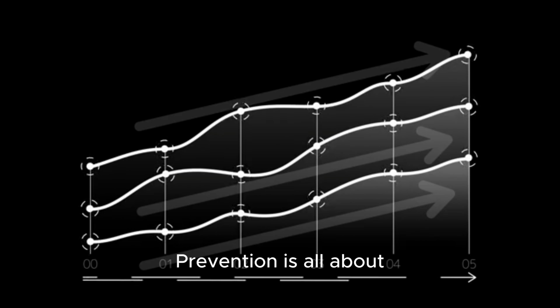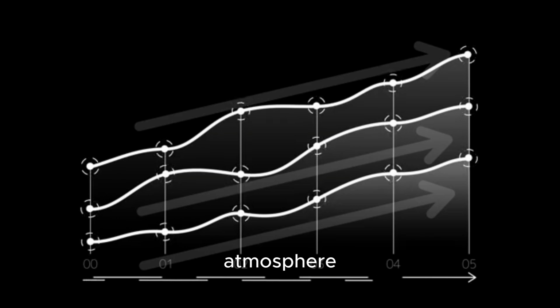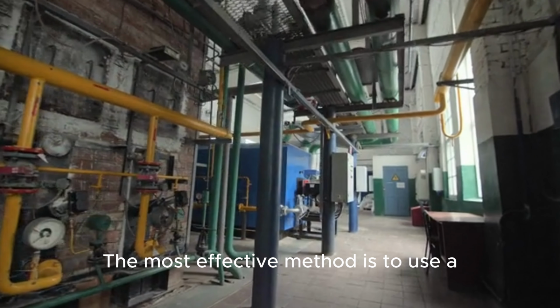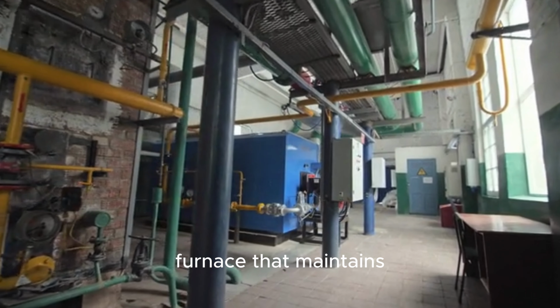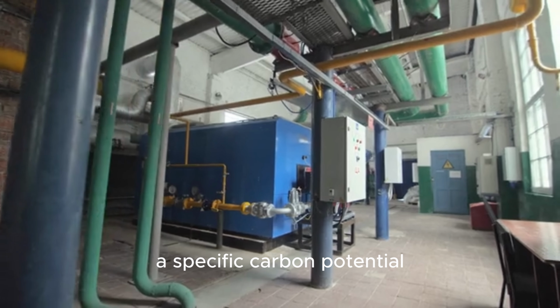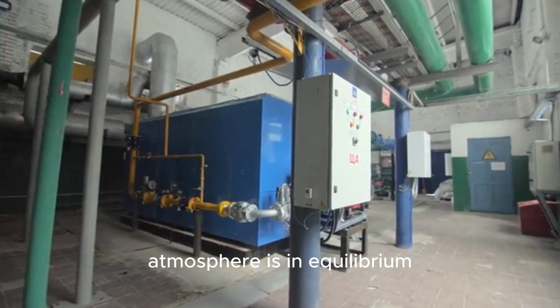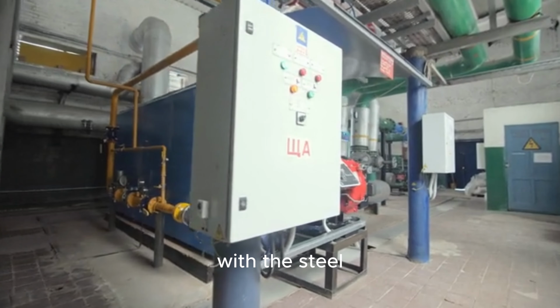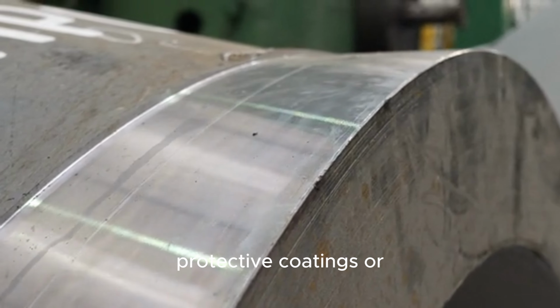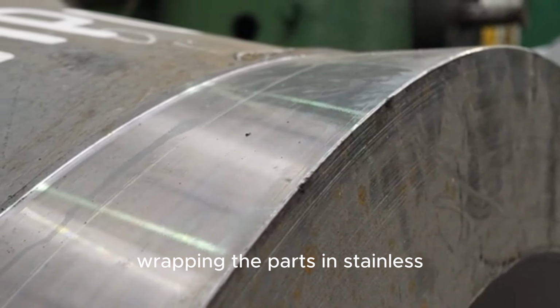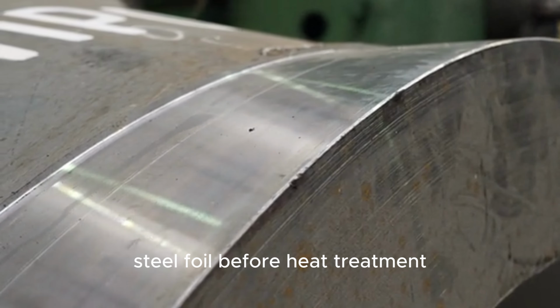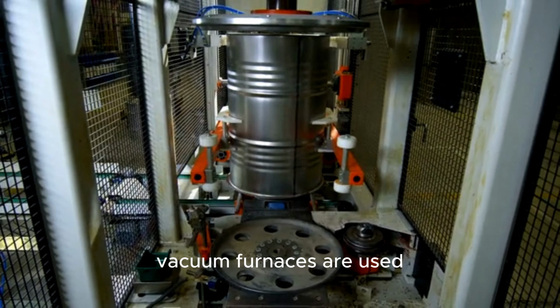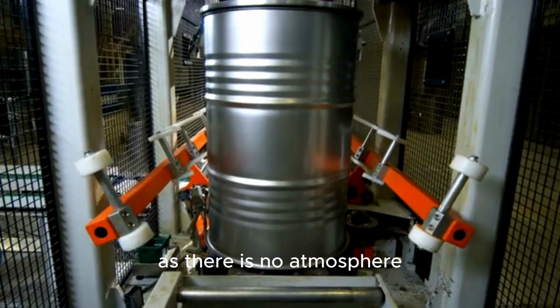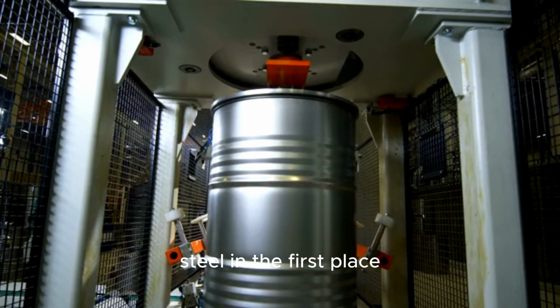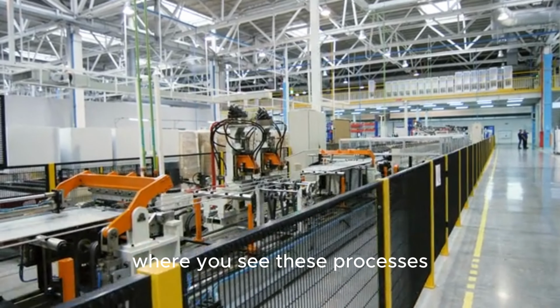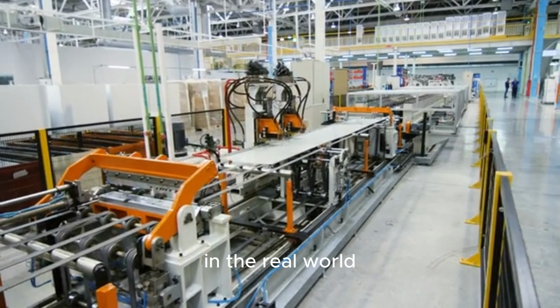Prevention is all about controlling the furnace atmosphere. The most effective method is to use a controlled atmosphere furnace that maintains a specific carbon potential, ensuring the atmosphere is in equilibrium with the steel. Other methods include using protective coatings or wrapping the parts in stainless steel foil before heat treatment. For the highest precision, vacuum furnaces are used, as there is no atmosphere to react with the steel in the first place.